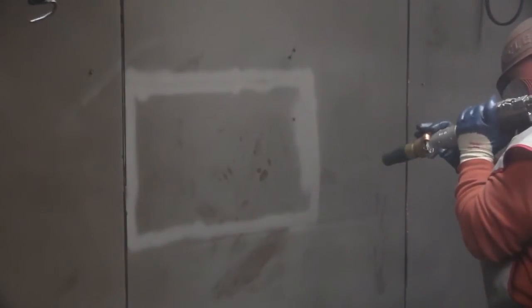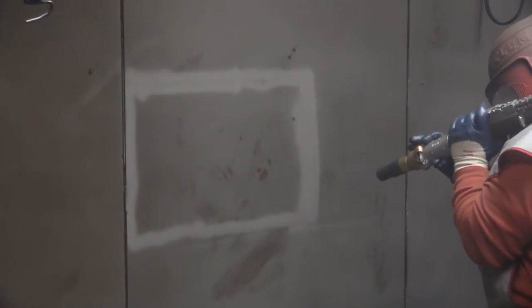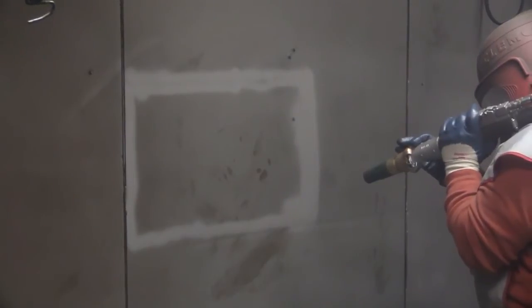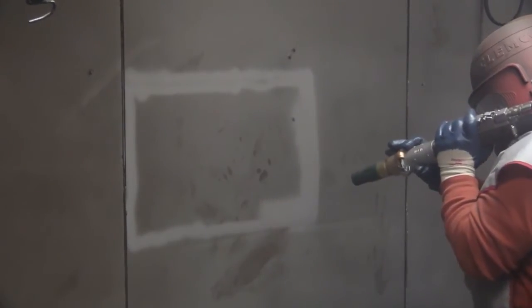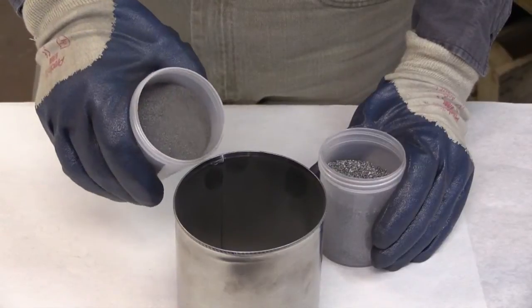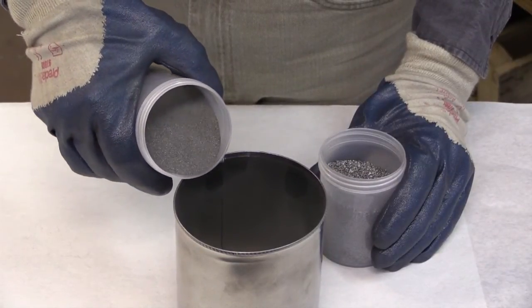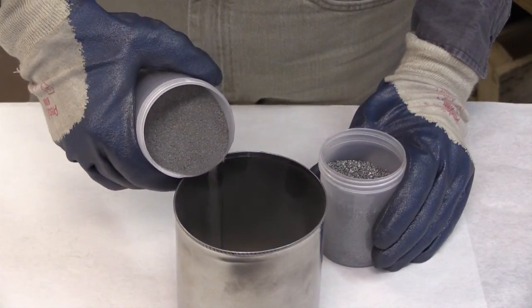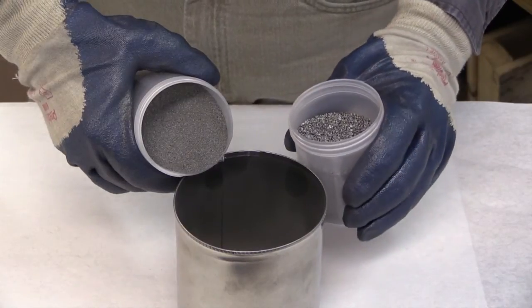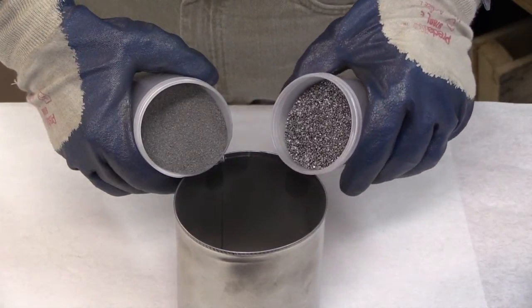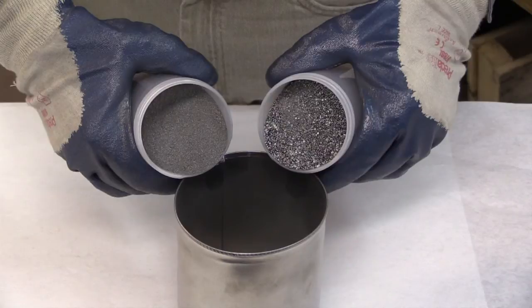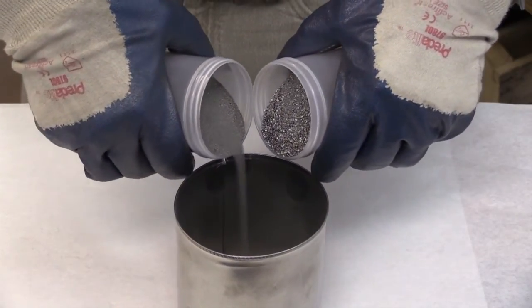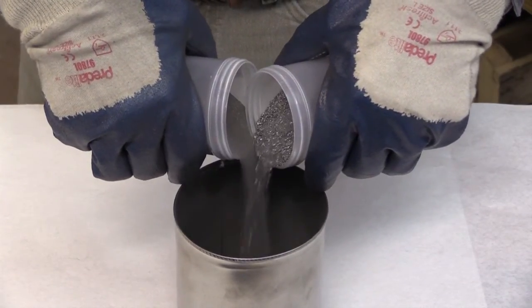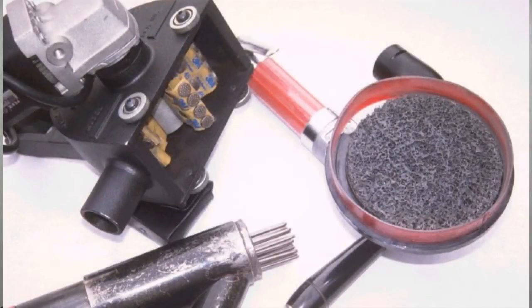Adjusting to changes in profile depth requirements and specifications is best achieved by selecting a different sized abrasive. For projects requiring a relatively shallow surface profile depth, a smaller abrasive should be selected. For projects requiring a relatively deep surface profile, a larger abrasive should be selected, but may be blended with a smaller abrasive to increase productivity. For power tool cleaning, the type of tool and the configuration of the impactors will oftentimes dictate the depth of the surface profile.